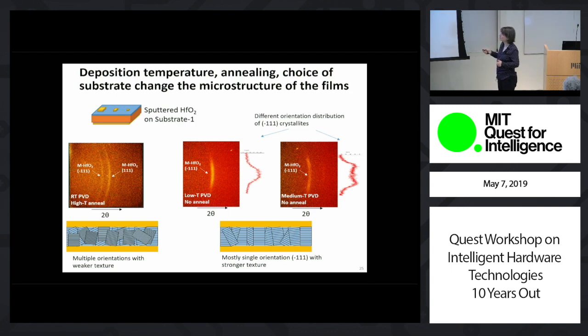And the point is that starting with hafnium oxide, by changing the deposition temperature, the annealing temperatures, as well as the choice of substrate, we could control the microstructure of the films, and we are correlating those microstructures to the electrical response of the hafnium oxide films. So for example, here, room temperature sputter deposited hafnia gives rise to multiple orientations with a weaker texture, that is just randomly oriented grains and grain boundaries.